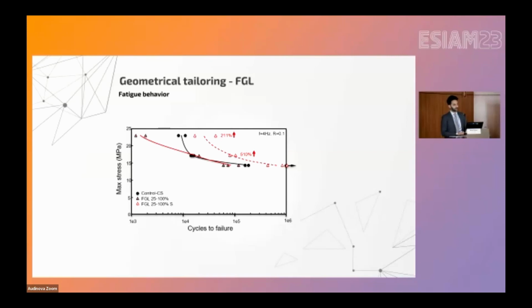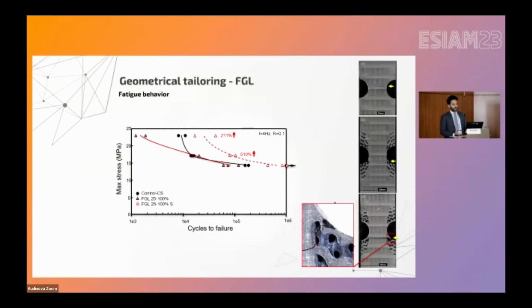But in the case where we included the lattice structure with the shell, we could see a significant increase in fatigue life. We had an increase of 200% and 500% in the mid-range fatigue life. And of course, the fatigue limit was hard to measure because of the run-out samples. The failure in most of the specimens was happening at the mismatch point where the stiffness was different, where we had the solid part and right next to it 25% relative density. So of course, we knew that this is something to work on.